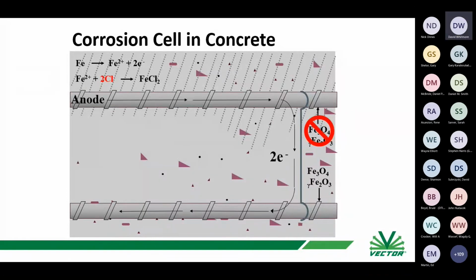Those electrons have to go somewhere. Okay, they're being generated by the corrosion process. They need to go somewhere. And so they will flow within this network of steel that's inside the structure. In our case, the Melan angles in this structure, but normally the rebar. They're typically going to flow to an area which we call a cathode. And at that location, they're going to react.